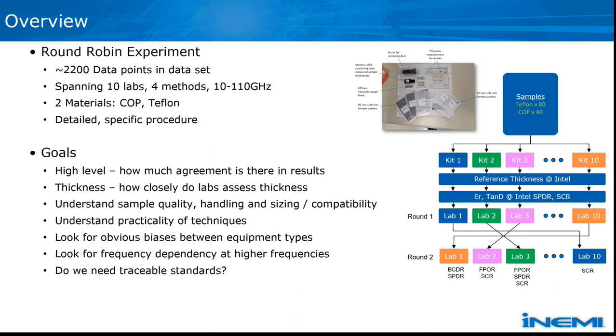And so we have cases where a particular sample was essentially measured by 3 labs using a variety of different techniques. And all of these samples came from the same fabrication batch. So nominally they're the same, but we also had the ability to look at individual samples.